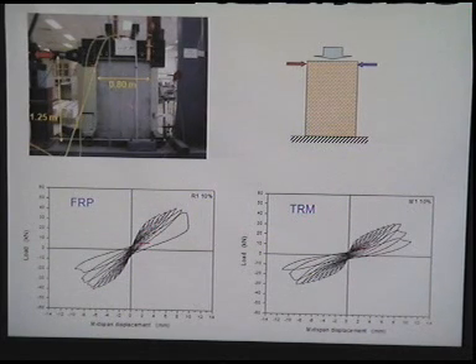A shear wall, for example, subjected to in-plane shear in combination with axial loading. In-plane shear is provided by an actuator in a dynamic way, so we have cycling of the loading. We always look at load versus midspan displacement curves, just to have a way of comparing the results. Red, in all cases, is the response of the masonry wall before any retrofitting, before strengthening. So there is a relatively low capacity. And then you see how the strength, but also the ductility increases. We have a number of cycles of loading if we use the FRP system. And then you see a similar response, similar results for the case of the TRM systems.